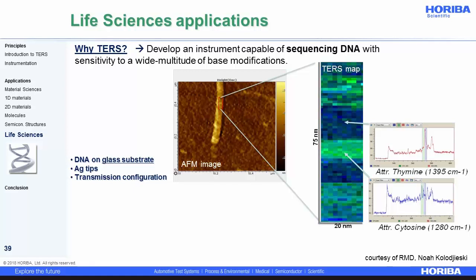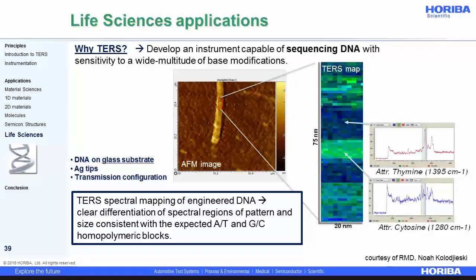This is the only example of TERS in transmission in this presentation, where the signal is collected with an oil immersion objective from the bottom. So you can see this TERS map, of about 75 nanometers by 20 nanometers, showing a clear differentiation of regions with pattern and size consistent with the expected AT and GC homopolymeric blocks. Indeed, we can distinguish on the right the two typical TERS spectra from both the thymine and the cytosine.